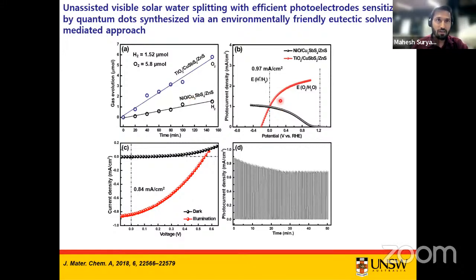Then we fabricated this Z-scheme system. You can see this crossover in the LSV curves, which was obtained by simply overlapping the LSV curve of the photoanode and the LSV curve of the photocathode. Even at zero potential, we can achieve a photocurrent density of about 0.97 milliampere per centimeter square, let's say about 1 milliampere per centimeter square. What does that mean? Without even applying a potential, we can achieve that photocurrent density.